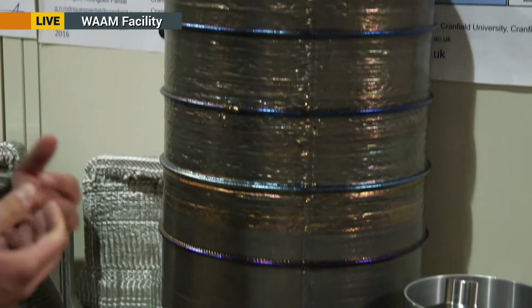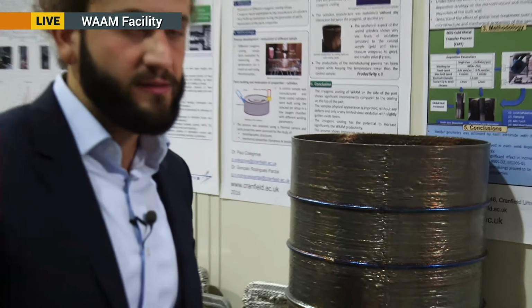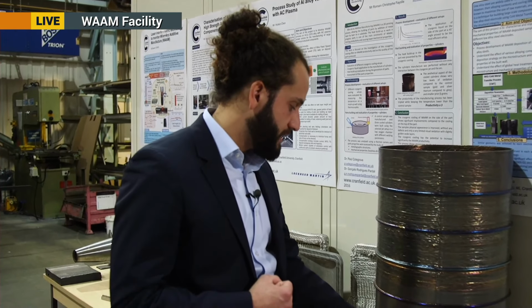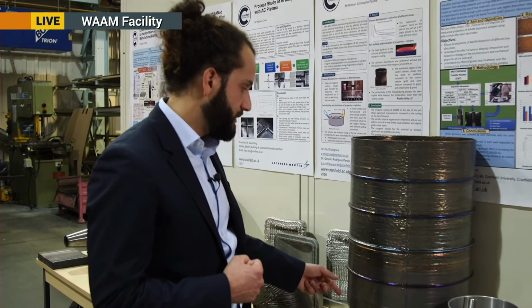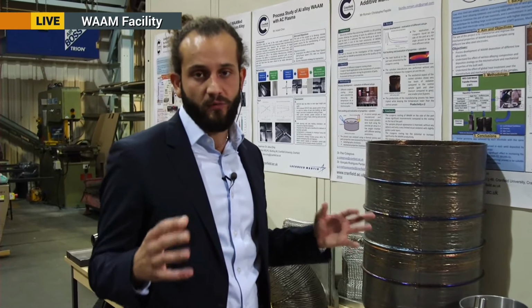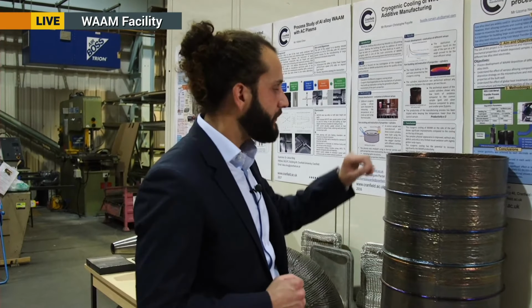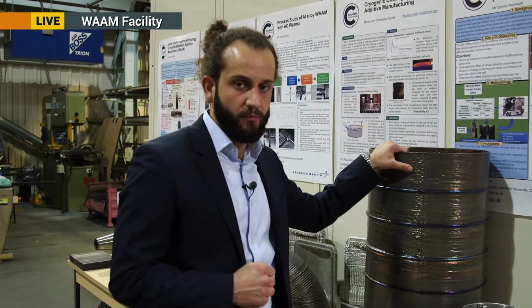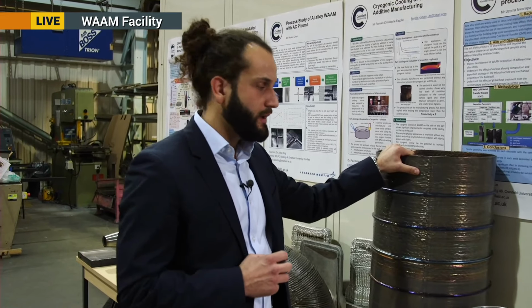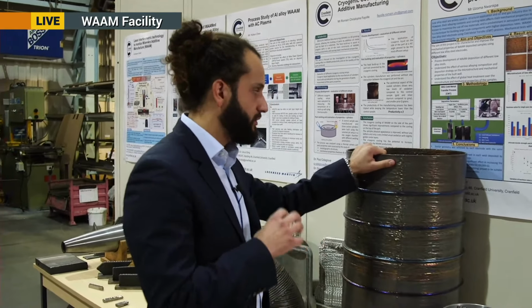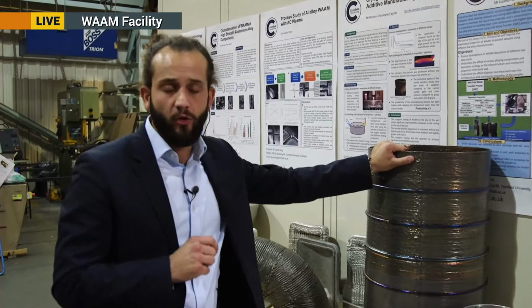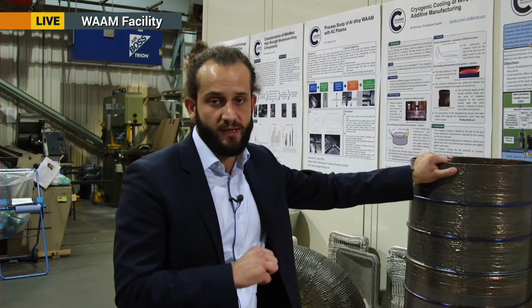Instead, again, by maximizing the manufacturing capability of additive, we've decided to start from a commercially available rod, really easy to get hold of. That's our substrate. We then printed on it the dome, and then we continue with the deposition of the actual main body of the cylinder. So instead of having 3 separated components and the associated supply chain, now we can do everything in one go. Then we go from the preform made by WAAM to the finished machine component, and by doing so we can reduce the amount of titanium which is wasted by over 200 kilograms for every tank that we made.